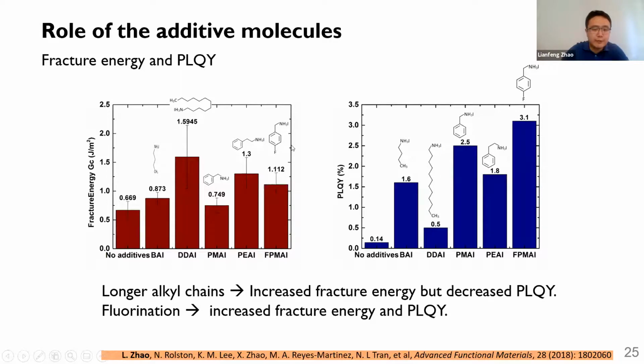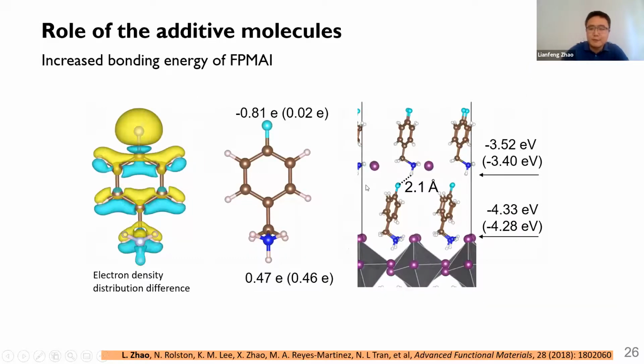On the other hand, if we introduce the fluorine, and compare the PMAI and FPMAI, both the fracture energy and the photoluminescence quantum yield increased. So in other words, we overcome the trade-off between optical and mechanical property by introducing the fluorine. We further tried to understand the mechanism. What we found is that because of the strong electron withdrawing capability of fluorine, the fluorinated additive has higher dipole moment and they form hydrogen bonds between these molecules. This greatly increased the binding energy and the interactions between these molecules, so that it increased the mechanical stability as well as the defect passivation effects.